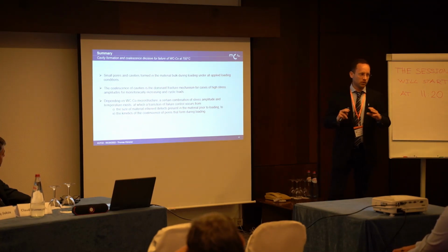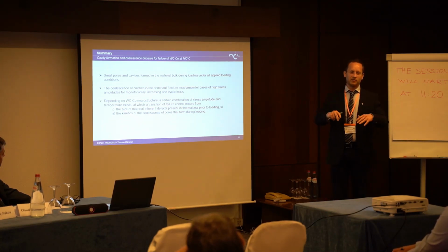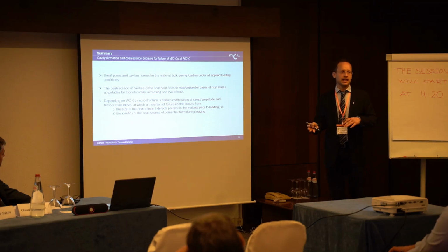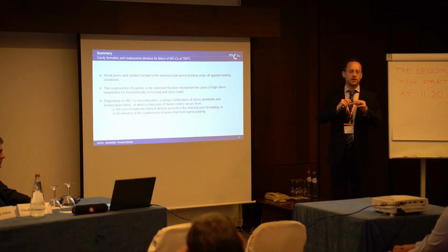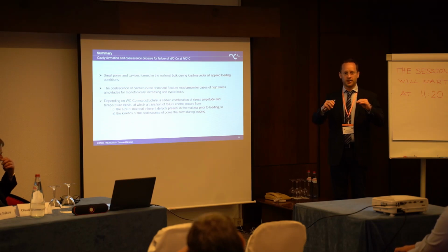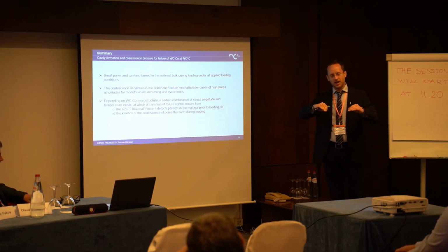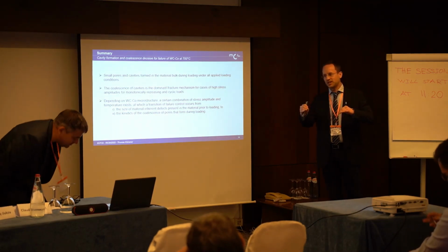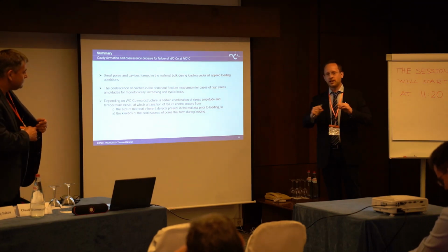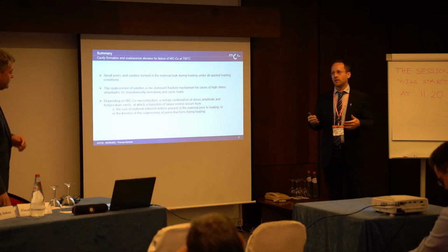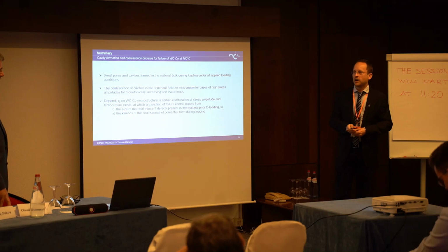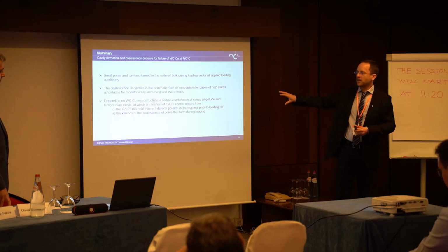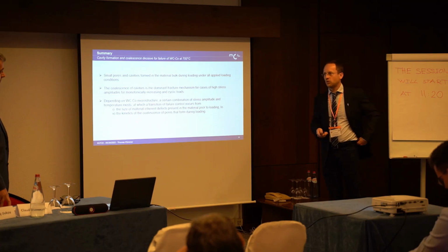And if you consider, we've done unpublished work on the effectively loaded volume of real milling tools, and they're very small because the temperature is high at the cutting edge. You see only very small effectively loaded volumes, in the order of magnitude of a couple hundred cubic micrometers. So this is, I think, very crucial to understand when we try to improve milling tool performance.